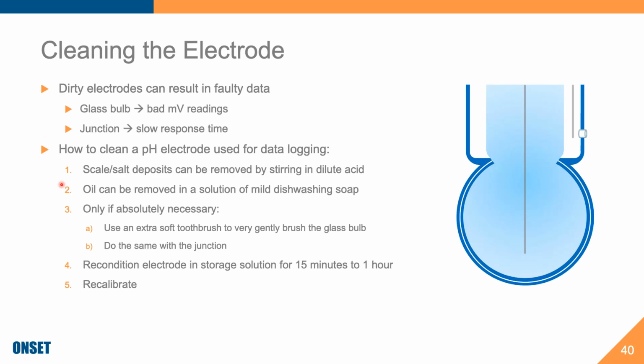Okay, briefly, because I know I'm running out of time. Cleaning the electrode. Dirty electrodes can result in faulty data. So if you have a dirty glass bulb, for instance, then you may get bad millivolt readings because those dirt spots are actually adding potentials to the overall potential of the system. And by adding those potentials, you're actually ending up with incorrect readings. You could also have a dirty junction. So here's your junction in this case, and if it's dirty or if it's clogged or even if it's dry and caked with salt, because these are high salt electrolytes inside, you will actually have a slower response time that may be slower than your interval between readings, which then gives you bad readings as well.